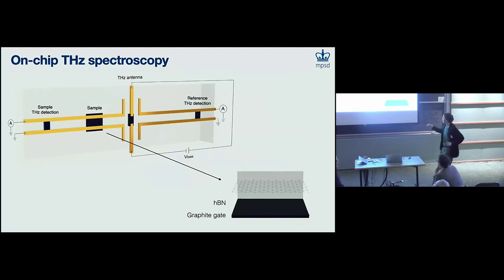So anyway, let's first just consider what happens if we have a square of graphite. The way that we integrate these heterostructures into these circuits, as I mentioned, is we put the heterostructure down first, then we build everything on top. So the waveguide pair sits on top of the material, and it's capacitively coupled. This is also not to scale. This is 10 microns. This is nanometers. So when the terahertz field comes by, it very easily comes down to interact with the sample.